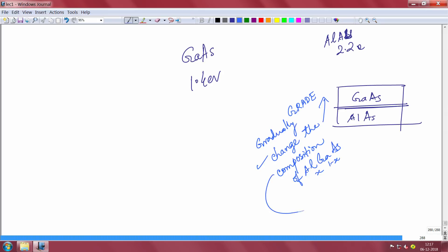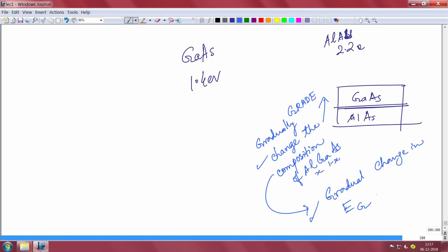This is x and this is 1 minus x — I slowly change x. Because of this, there is a gradual change in various properties like band gap, electron affinity, dielectric constant, and other things. Most importantly, your band gap will gradually change. This has huge implications in practical devices used in white light LEDs, and in transistors going into cell phones for RF transmission and receiving modules — made of indium phosphide/gallium arsenide HEMTs and HBTs. This gradual grading is actually used in commercial devices.